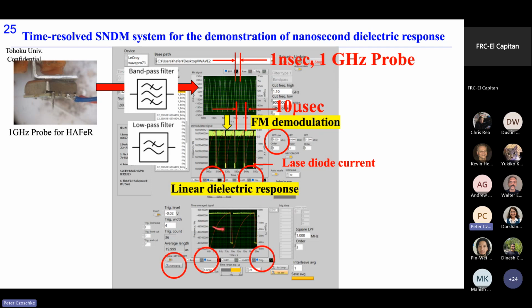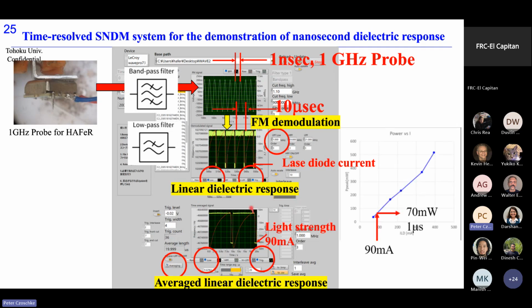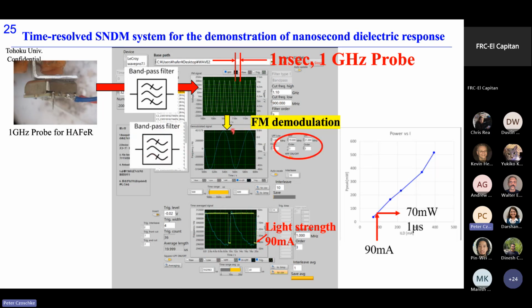By taking the time average, we obtain the linear dielectric response after noise reduction with an improved signal to noise ratio. So this is the average linear dielectric response. This is also the measured laser beam waveform, and this means a 70 milliwatt, 1 microsecond laser pulse is irradiated to the sample. Then we change this filter to a band pass filter and obtain this waveform by setting the filter condition. The period of this waveform is 50 nanoseconds. This means that we apply the AC bias voltage with a frequency of 20 megahertz. So this is a nonlinear dielectric response signal.